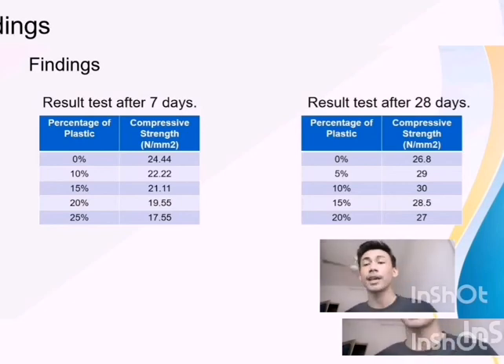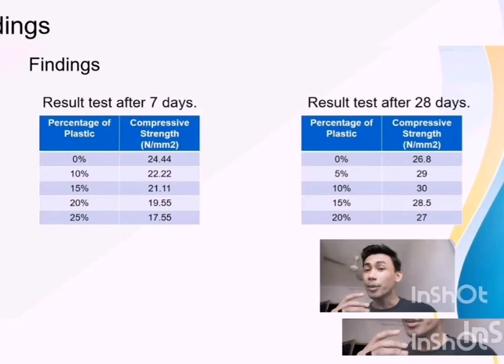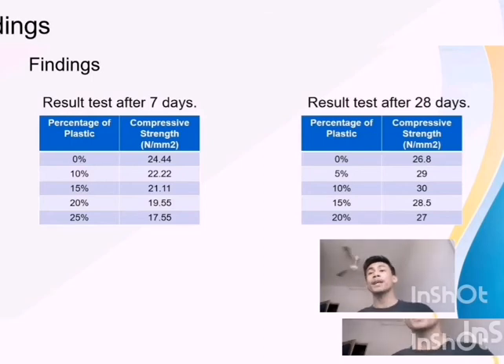But we can see with the last test, which is 28 days. From the result after 28 days, the natural concrete with no plastic has a compressive strength of 26.8 Newton per millimeter squared. After we added 5% plastic, its compressive strength increased to 29 Newton per millimeter squared, then 10% gives 30, 15% gives 28.5, and 20% of plastic has a compressive strength of 27 Newton per millimeter squared.